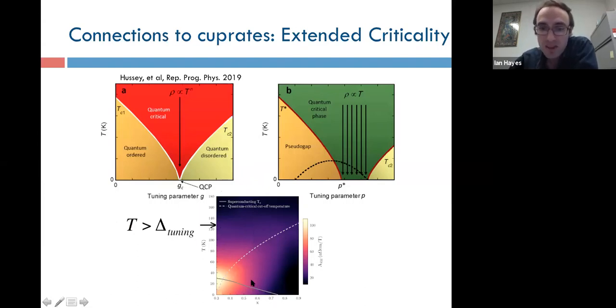And you can cross below that, but that doesn't result in a continuous decrease of the effect down to 0 at 0 temperature. The effect sustains itself for all superconducting samples. And so it almost makes it seem like in the pnictides, you can see two energy scales. You can see the main detuning energy, which gives you this fan-like region and some region of doping independence in the Hall response. Then there's some other energy or time scale that makes those fluctuations, or the effect of those fluctuations in the transport, non-zero all the way down to zero temperature. There's something that sustains the effect throughout this region. So that'll be an important avenue to consider in the future.